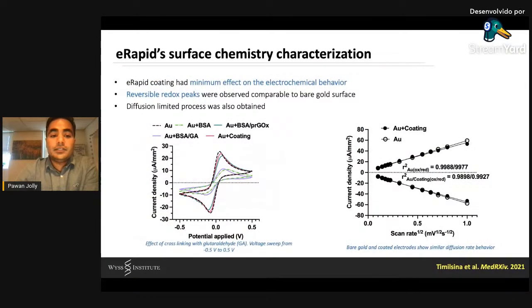Taking a step further, we also looked into electrochemical characterizations. You can see a really good reversible redox oxidation and reduction between the bare gold and our coating. It also has minimal effect on the electrochemical behavior compared to the gold without coating. You can see a very similar diffusion rate, which really shows that it is a diffusion limited process.